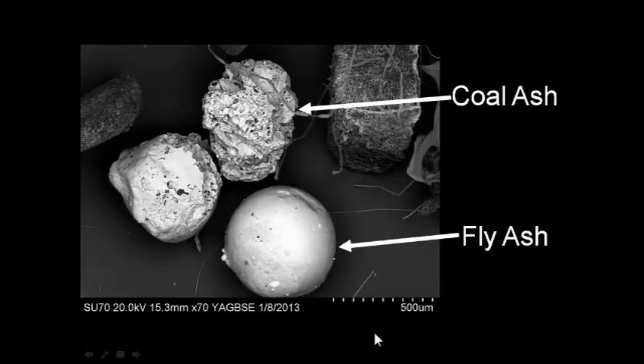So like I said, in 8 of our 21 samples, on average, about 20% of the sample was ash. So we had to adjust our numbers. If you've been at all keeping up with the mass media attention of this study, you'll see that the numbers have changed in time, and that's a result of this SEM analysis. So that tells us about some of the particles.